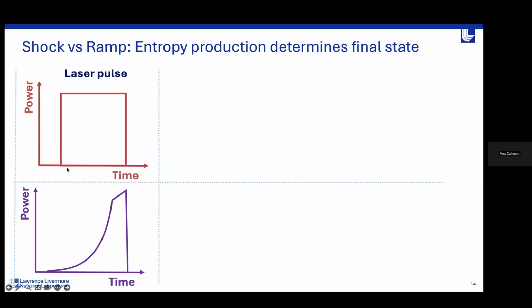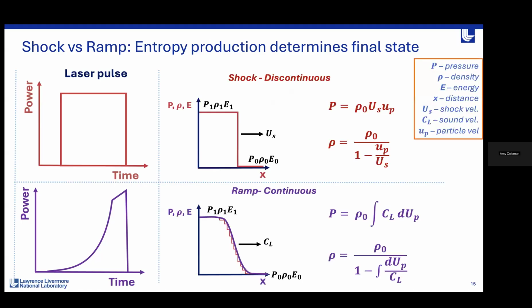For a shock compression, you have something where the laser power is on and it's held for a while and it's turned off. And this sudden, intense wall of laser intensity launches a very sharp and rapid compression shock through your sample. In contrast to this, if we're doing ramp compression, you'll notice there's a marked difference in the pulse shape. We have something that's more gradually increasing in power as time goes on. And when we're doing these types of compression, obviously we are conserving mass, energy, momentum. But the way that this looks in these two types of compression is slightly different.